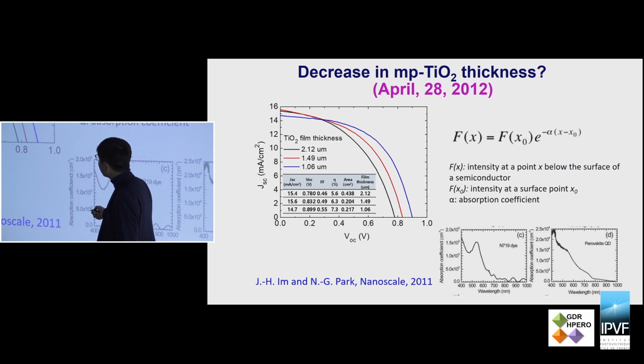So we decreased the film thickness from 2 micrometers to 1 micrometer, and then we observed a gradual increase in power conversion efficiency, which is due to the increase in open circuit voltage and fill factor you see here, without sacrificing the short circuit photocurrent density. So this relationship is actually proved.